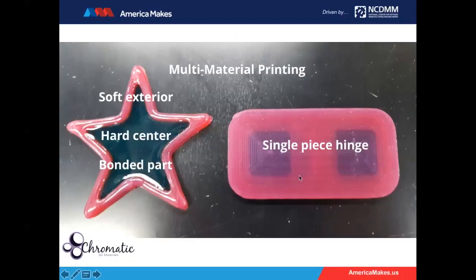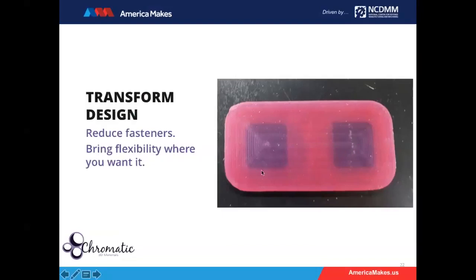We also have a demonstration of a single piece hinge. Here, the dark purple areas are a harder durometer than these pink areas that are softer durometer. What that means is that you're able to print a part that is more likely to flex right in the center here. And so when we start to do this, we can imagine part designs where we're able to reduce fasteners and get the flexibility exactly where you want it.